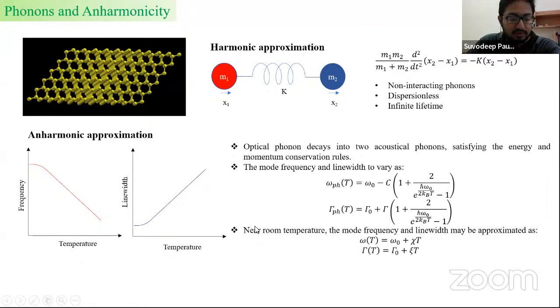So importantly, what we see is that when the temperature is not too high, we may approximate these curves to be linear in temperature, with a negative slope for frequency and a positive slope for the phonon line width.